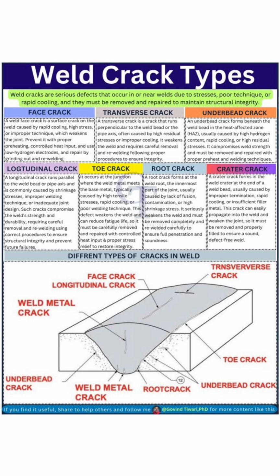Underbead crack. Underbead cracks form beneath the weld bead in the heat-affected zone, or HAZ. Caused by hydrogen content and rapid cooling, they're tough to spot but dangerous. Fix with proper preheat and welding technique.